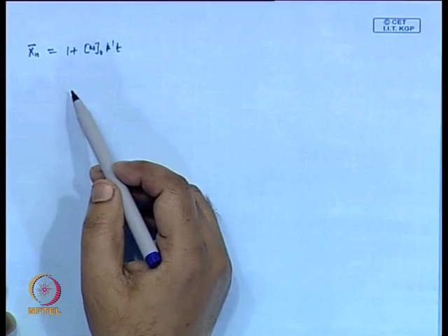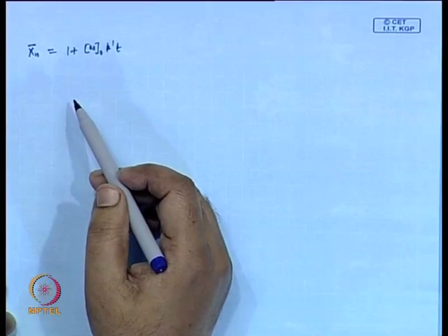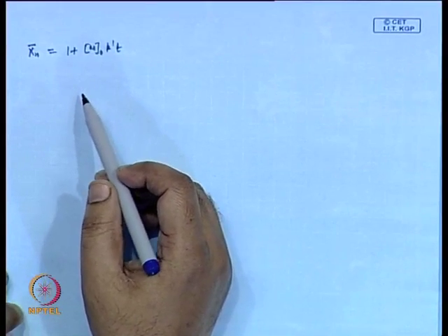That is why typically these reactions are done at very high concentration in solution, or in some cases in bulk. That means you take the monomers as such, which ensures the maximum possible concentration of the monomeric unit.